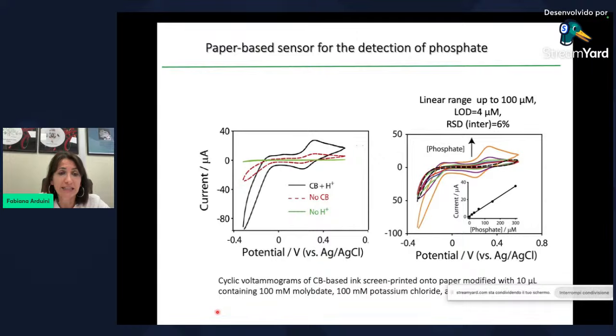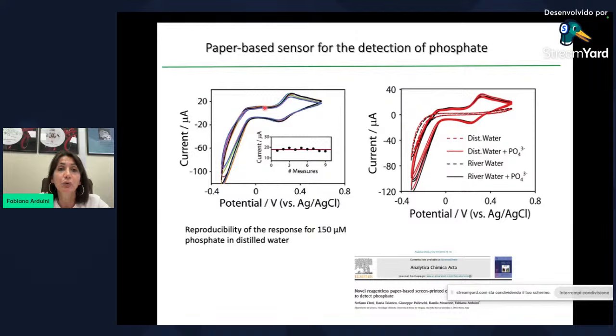And another important thing, because this is the first work in which we use filter paper, we demonstrated good repeatability and also the capability to detect phosphate in distilled water. Why is it important? Because it demonstrates that by adding distilled water, these few microliters are enough to dissolve the reagent. So we have an exact pH to make the measurement, and we also obtain a good response